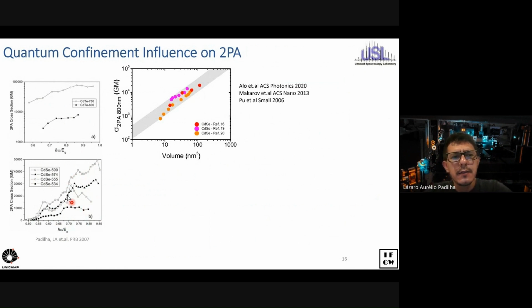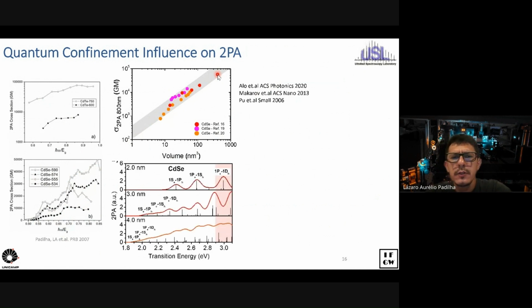And in fact, when we take data for cadmium selenide, for example, from several papers out there and put it all as a function of the volume, what we see is this very nice volume dependence. We get everything in a line here, which indicates that two-photon absorption in fact increases with the volume, and that's a linear dependence, which means that apparently it doesn't depend on the size if you think in terms of the volume-normalized two-photon absorption coefficient.